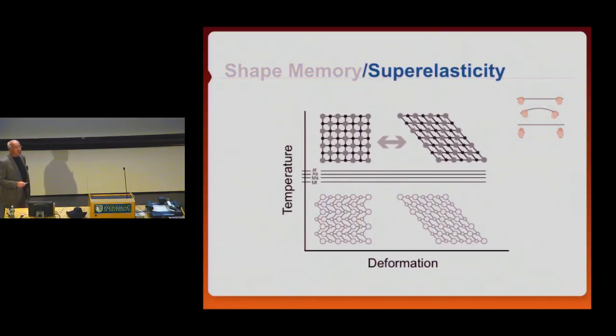There's another effect in this whole thing, and that is when you take this austenitic structure above AF and you deform it, it does not deform through conventional dislocation movement, but it goes directly into de-twinned martensite. That's what we call stress-induced martensite. Stress-induced and deformed martensite. So in this one, this whole thing is above AF. So if you are above AF, above this transformation temperature, you can deform the austenite into deformed martensite, but when you let go, it springs back and it just reacts extremely elastically.